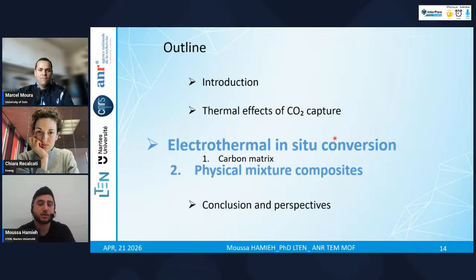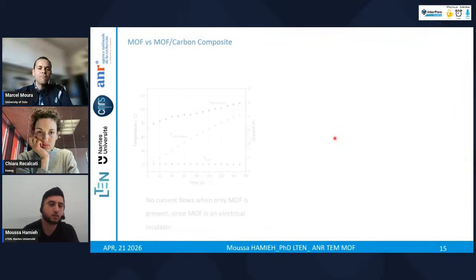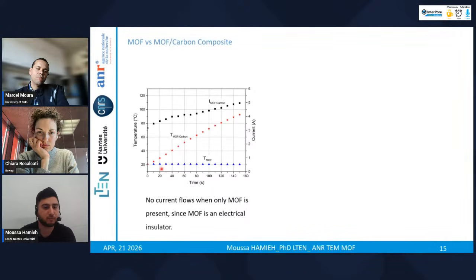After we understood the carbon and its behavior, the next step was to integrate the carbon with the MOF and evaluate the behavior of these composites. We first compare the behavior of the MOF alone. Here it's the temperature of the MOF as a function of time. No current was flowing in the MOF alone, so we have no increase in temperature. This is because the MOF is electrically insulating.